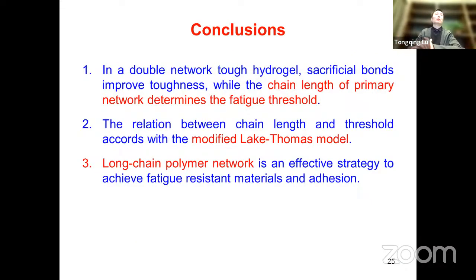Okay, so here's the conclusion. We find that in a double network hydrogel, the sacrificial bonds will improve the toughness, but the chain length of the primary network will determine the fatigue threshold. So these two properties are totally different. Second, the relation between the chain length and the threshold accords with the modified Lake-Thomas model, and we have performed many experiments to verify this. And third, we find that this long chain polymer network is a very effective strategy to achieve fatigue resistant materials and fatigue resistant adhesion.